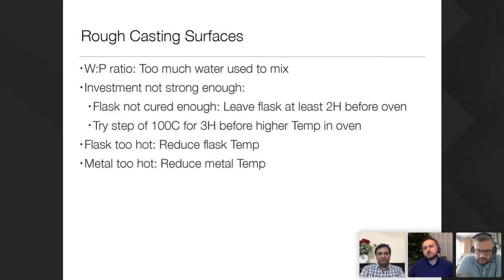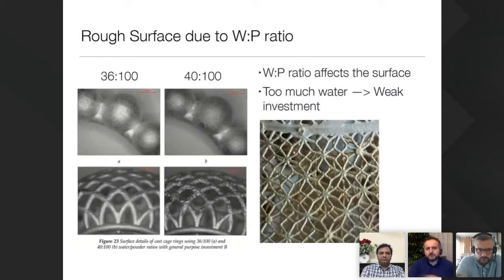Yeah. So first of all, if you put too much water, you will have rough casting surfaces, and also your investment will be weaker. You remember we said we want a strong investment, which is good for the resin, for the whole expansion part of it. If you don't leave your flask enough on the ground, at least 2 hours before putting it in the oven, or you may also use that step of 100 in the oven to remove this humidity, your investment will not be strong enough. So these are the issues seen on the rough casting, but I will give some examples here.